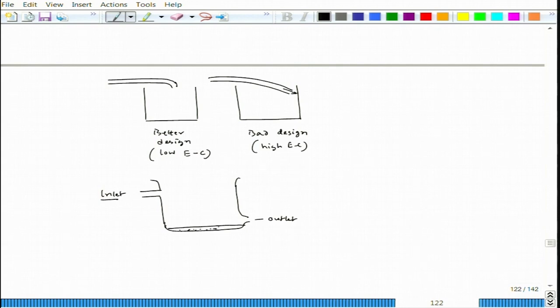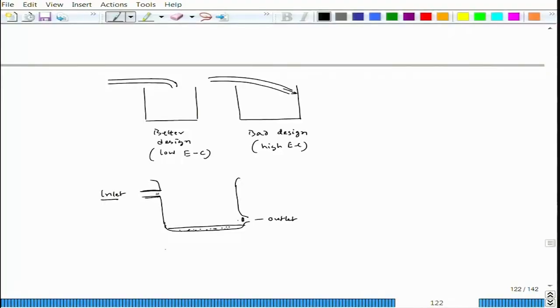Now, the major problem is these dust particles. See, dust particles can also clog this particular pipe. Here, in the inlet case, there is a possibility of clogging, but the clogging would be much less compared to this, because depending on the flow rate one can have a kind of deposit here. Here also you can have a deposit, definitely. Now, that deposit can lead to a problem, because once you reduce the thickness of the pipe, the speed increases, and that speed leads to turbulence, because there is also a blockage, and that turbulence will create a lot of erosion corrosion.